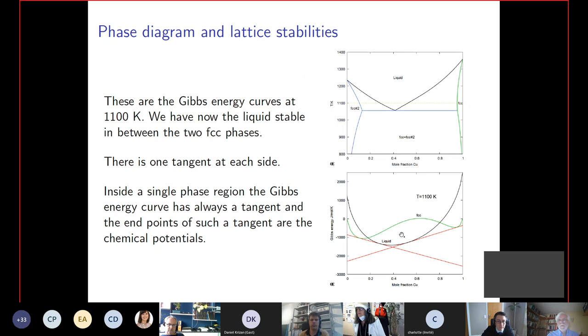And if you go up in temperature, the liquid becomes stable. So you still have the miscibility gap in the FCC phase, but the liquid is now more stable. So you have one tangent on the copper-rich side and one tangent on the silver-rich side, and you have these two tangent curves with the chemical potentials. So this is the basic technique. You describe your Gibbs energies, and you can calculate the equilibrium by minimizing the Gibbs energy for the values of temperature and composition you have.